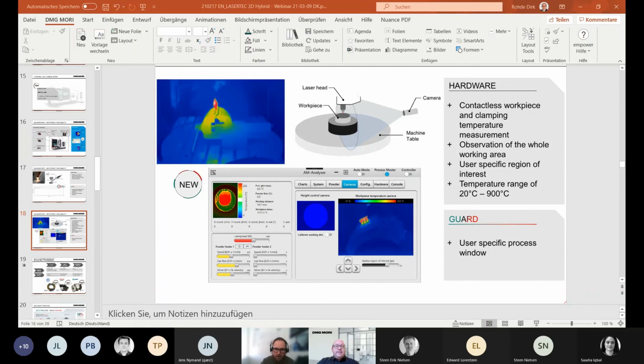Yeah, I think that also covers it, or if she has a follow-up question, do you play mostly with laser power? We also do a lot of parameter testing where we change the laser power, the feed rate, the print speed, and everything. Is that any different to your machine? Which parameters do you focus mostly on? No, that's the same. It has to do with feed rate, speed, and laser power. Laser power itself is adjusting. I said that we have a temperature watcher of the melt pool. If this is going too big or the color changes in a manner that you don't want, laser power is reduced automatically, also depending on the geometry.